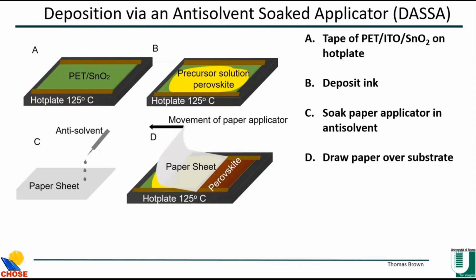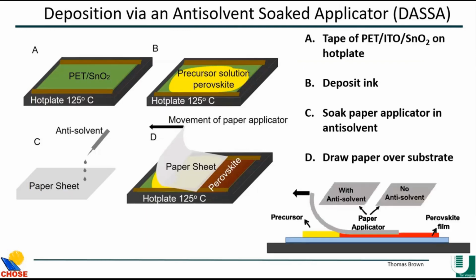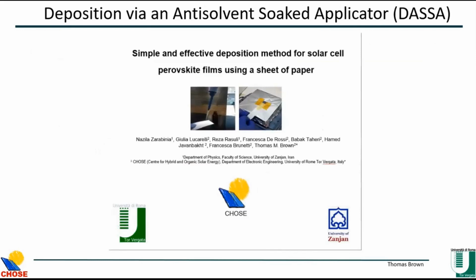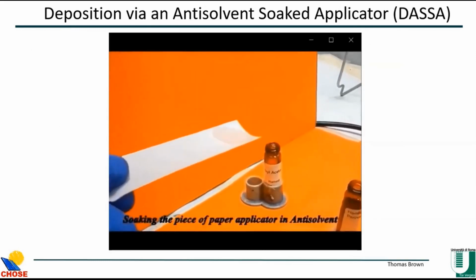So this is what we did. We applied PET ITO SnO2 on a hot plate so we could control the temperature. And it was taped on with 50 micrometer tape. We applied the perovskite solution, and then we tried different applicators, soft applicators, including tissue, paper, polyamide, and we drew it over the ink, and at the trailing end, you'd form a film. Now, in one case, we'd apply anti-solvent on the paper applicator before deposition, because we thought this was going to be key. And this is just a cross-section of this method, but the best way to really show this manual method at the moment is to show a video.